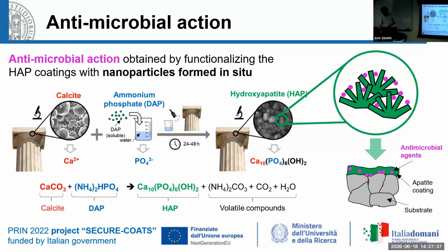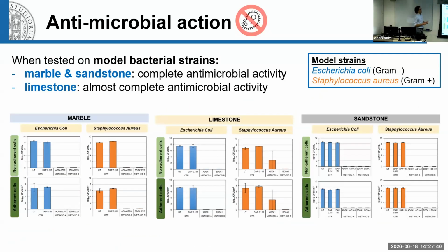So what we found was that we started with model bacterial strains, so strains that are used in the biomedical field, Escherichia coli and Staphylococcus aureus. Later, we replicated with also environmental strains, so bacteria that are present on architectural surfaces. What we found was that for different types of substrate, as you can see here, differing in terms of composition and microstructure. In the untreated reference, we placed a certain amount of bacteria, they stay there.